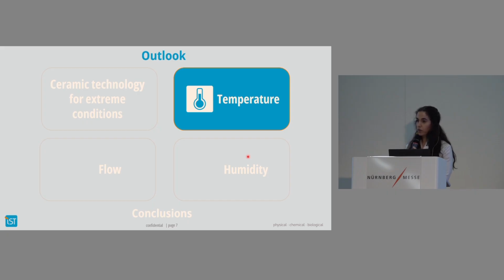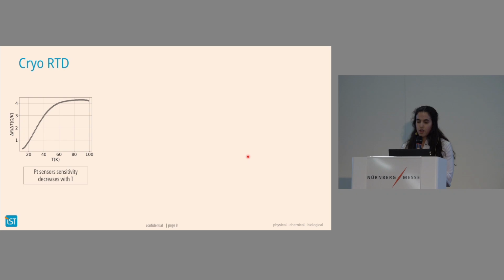So moving forward into that and starting with temperatures, over the years, we had many projects that were dealing with very high temperatures. And the natural question for us was if we could develop similar sensors that could be used for extremely low temperatures. Here the challenge, and this is what you can see in the plot here, is that the sensitivity of the platinum sensors decreases a lot at low temperatures. Here you see how much the resistance changes with the temperature versus temperature. And this is what one sees here.